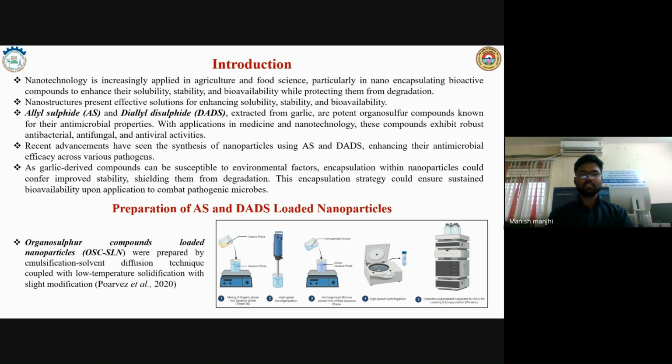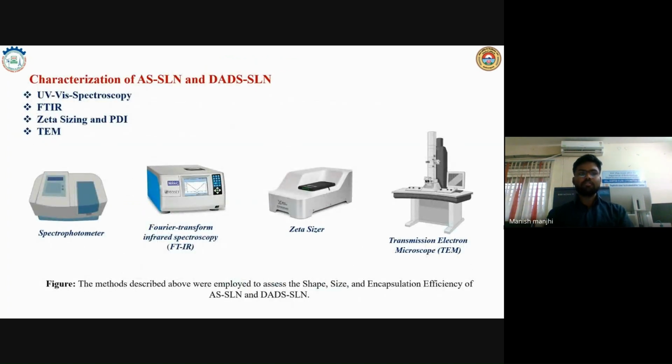So I'm trying to encapsulate these organosulfur compounds in solid lipid nanoparticles to stabilize them and increase their stability. These organosulfur compound loaded nanoparticles were prepared by the emulsification solvent diffusion technique coupled with low temperature solidification, with a slight modification by Poarvez et al. Now, I've characterized these allyl sulfide solid lipid nanoparticles and the diallyl disulfide solid lipid nanoparticles using UV-visible spectroscopy, FTIR, zeta sizing, PDI, and TEM.